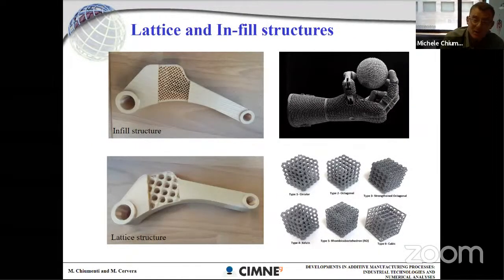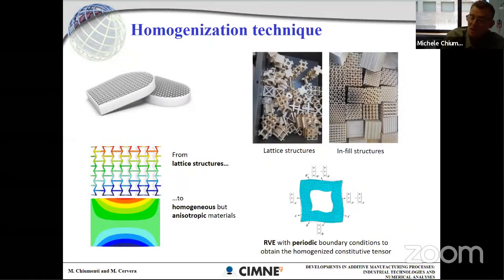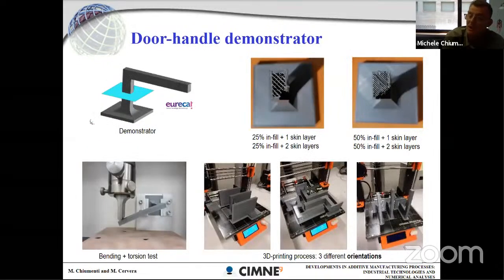Next step is to define the behavior of the lattice structure. Well, in this case, you have lattice structure or infill structure. At the moment, we were working with infill structure, so typically 45, minus 45 rasters. So what's the solution? The solution is to go from the actual lattice structure to one homogenization of this lattice structure. And the result is once again an anisotropic constitutive tensor. So here we are using periodic boundary conditions, and we are obtaining the constitutive tensor for this material.